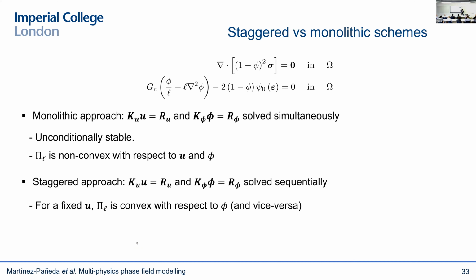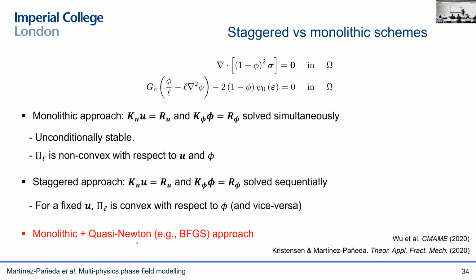And the other approach, which is far more popular, is what we call a staggered approach, where you solve them sequentially, and people will typically use the single pass staggered approach, where the functional is convex with respect to the displacement for a fixed phase field and vice versa. So this is what people use, but then you lose this unconditional stability, so it's not ideal. And what we have suggested is to use a monolithic approach, but using quasi-Newton methods such as BFGS. And this seems to be working very, very well.